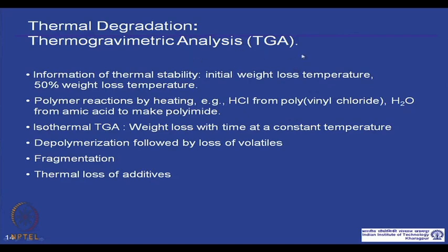Now, if you increase the temperature of a polymer, polymers typically degrade. This is very important from a processing point of view, because while processing, the polymers are subjected to a very high temperature, and as we have seen, TG plus sometimes 150 degree centigrade, or TM plus 50 degree centigrade, or even more. And under shear, in case of processing, we are applying this with the screws, and so in case of molding, which means that it undergoes shear. So, polymer might degrade and decompose under those conditions.